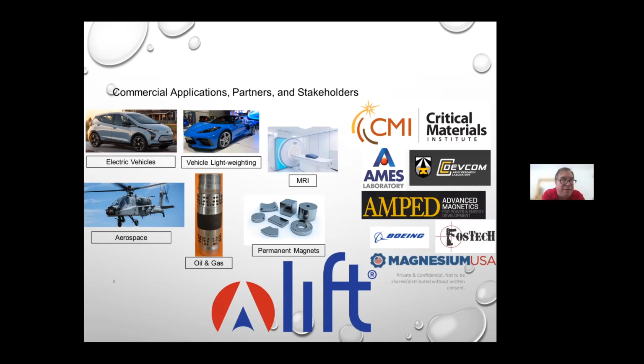There's a lot else going on in history, but we're really here to reach out for partners, stakeholders, collaborations. We are particularly good at making high purity and low oxygen, phase pure, difficult to fabricate powders and agglomerates and high surface area materials, controlling oxygen, carbon, nitrogen, and other contents for lightweighting, electric vehicle, aerospace and defense applications, as well as oil and gas, which is one of our larger businesses. So we are actively looking for partnerships, collaborations, and really are pleased to be a sponsor member of LIFT and to be involved in this partnership.